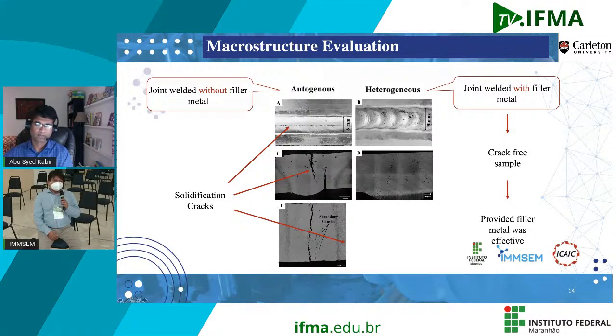And as expected, we got a large amount of solidification cracks in the autogenous joint, and we created a crack-free aluminium 7075 welded sample with the use of only 1.7 weight% nanoparticle.